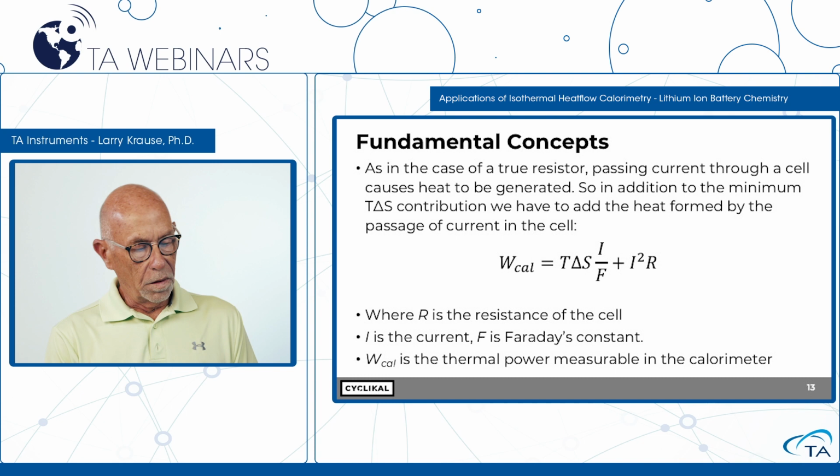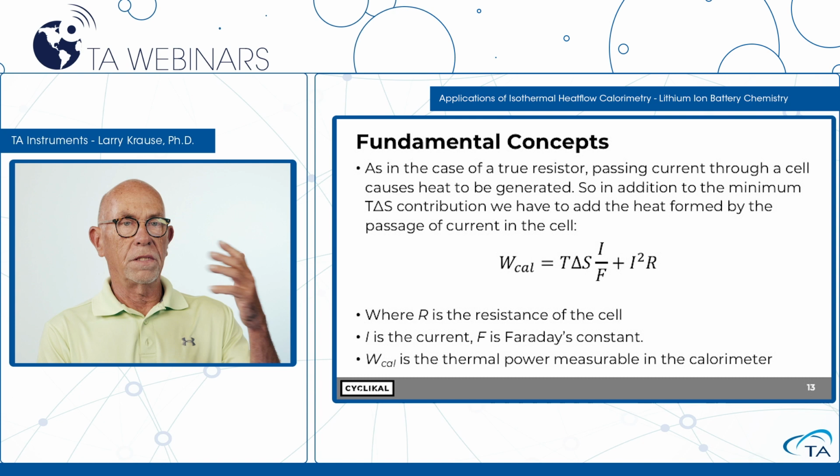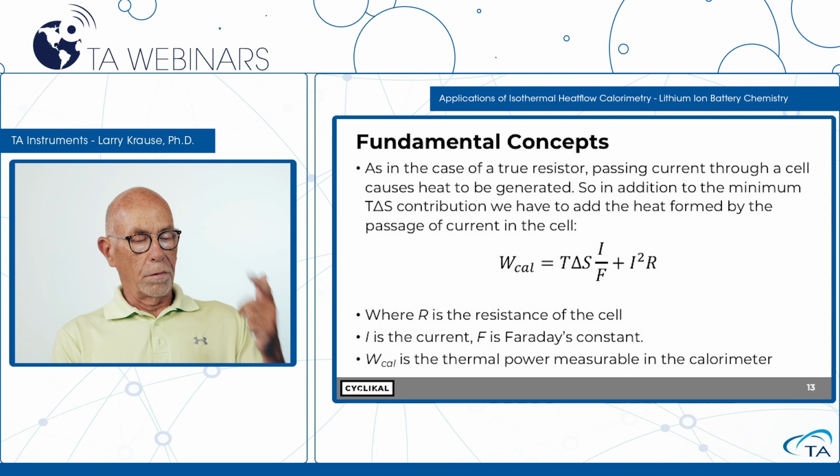W sub cal represents the thermal power that we're measuring in the calorimeter. Here's our T delta S term, and we're converting this to a heat flow. T delta S itself is in energy, but by multiplying by the current divided by Faraday's constant, we convert that to joules per second, or a thermal power. And now the